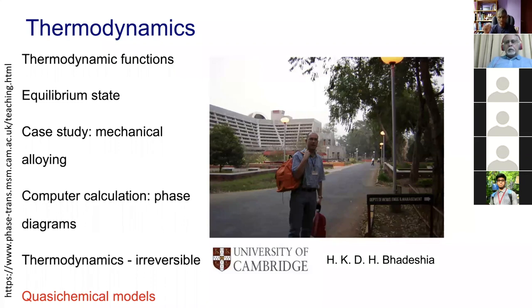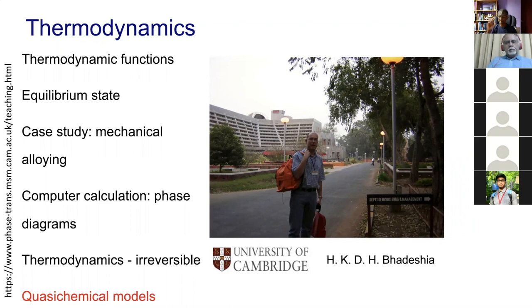The model I'm going to describe has a variety of hierarchies. The regular solution model is known as the zeroth-order quasichemical model because it basically assumes random mixing for the entropy term with a finite enthalpy of mixing. Today I'll discuss the first-order quasichemical model, where we look at pairs of atoms rather than individual atoms.